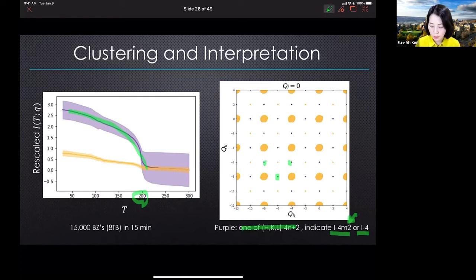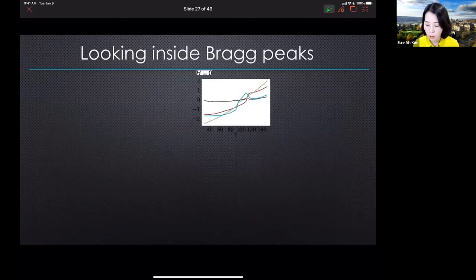Now, in order to gain further understanding: compared to the reciprocal space that I showed you at the beginning, this looks very simple. The reason it looks simple is because we lumped all the reciprocal space points near the Bragg peaks to behave together. So then what we did was to open them up and let all reciprocal space points have individual choice in which kind of behavior they find themselves in. We allowed for more clusters. The number of clusters is determined empirically at the moment. We change the number of clusters and watch whether the results change. For this data set, we found that beyond four, all results were essentially identical to having four clusters. So we settled on four clusters and found these four different behaviors.